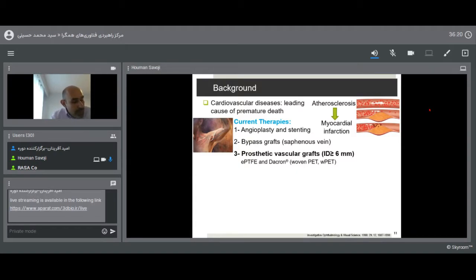So, but most of the time now, when you look at the companies or commercialized vascular grafts in the market, most of them have a large diameter, more than 6 millimeter. However, the coronary arteries have a small diameter, less than 6 millimeter. And the material that companies usually use to make these vascular grafts is Teflon and Dacron, that we call PTFE.